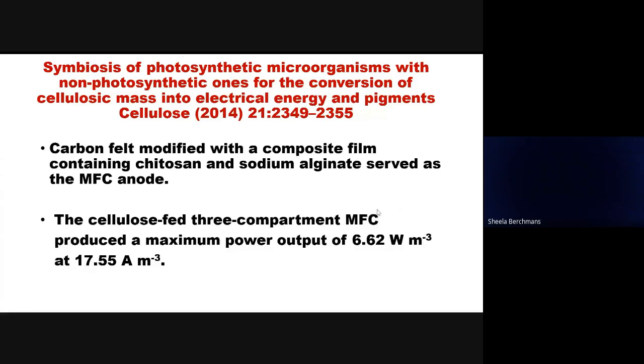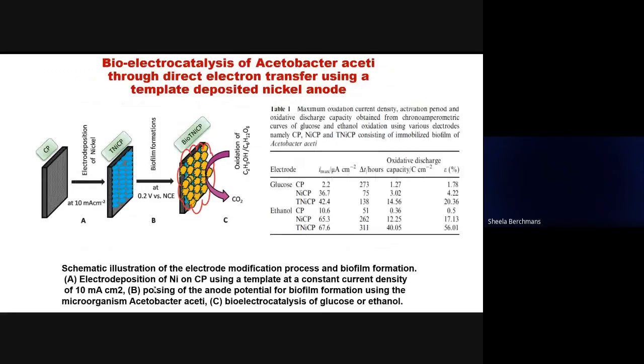And the same fuel cell, we could extend it by modifying the anode with the chitosan and sodium alginate film, which functioned as the anode. So the cellulose fed 3-compartment MFC produced a maximum power output of 6.62 watt per meter cube at 17.55 ampere per meter cube.